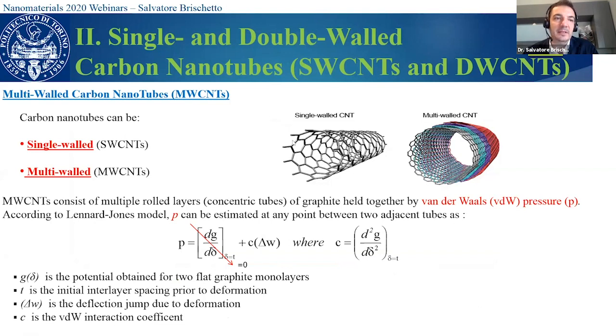Then another possibility is single-walled carbon nanotubes and multi-walled carbon nanotubes. In the case of multi-walled carbon nanotubes, each single nanotube is linked with the other by means of the van der Waals forces. So this is a way to consider the van der Waals forces by means of the coefficient of interaction C and the deflection jump due to deformation.